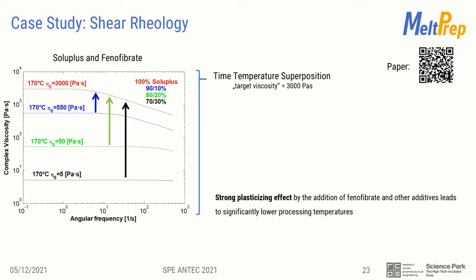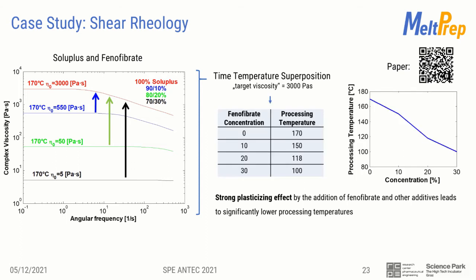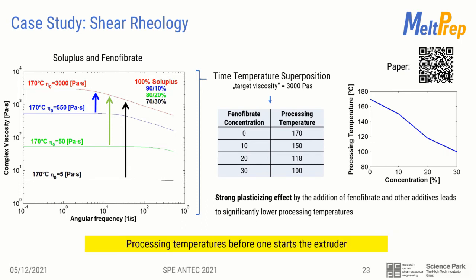The time-temperature superposition allows you to shift those curves to different temperature levels. You can predict operating temperatures before you even start the extruder. In this case, it predicted the temperature decrease from 170 degrees C for the neat polymer to 100 degrees C for the polymer API mixture. And the best of it, it just worked perfectly when we turned on the extruder. Literally no process development was required.